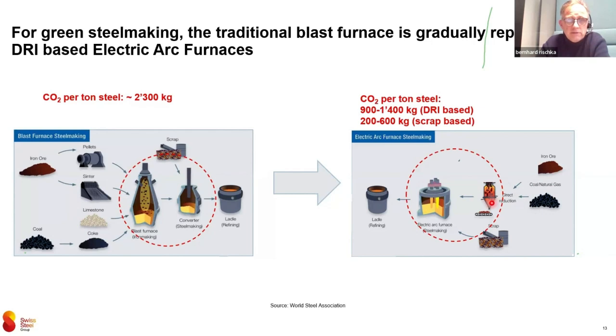This is an established process happening all over the Middle East. You can start in Saudi Arabia, in Qatar Steel, in UAE, in Emirates Steel, in Hadeed. So this is a proven process which would already bring your footprint from 2,300 kilos to approximately 1,400 kilos. And as a second step, if you want to reduce the iron ore with green hydrogen instead of natural gas, then you would go again to a much more dramatic reduction in CO2 emission. Yeah. There are just two problems.